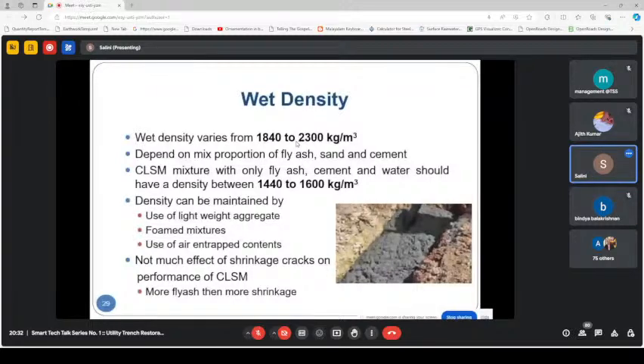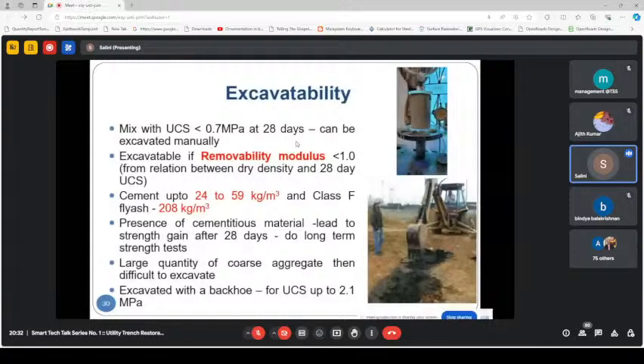Then excavatability, as I said, is very important. Sometimes what will happen is we add more cement, we add more fine aggregates, and the compressive strength becomes more than what is required. In such cases, it becomes very difficult to excavate. And then if there is some leakage, or if some widening is happening and we need to relocate the utility, it becomes very difficult. So make sure that strength does not go beyond what is required. In order to show that we have done it properly, we may increase the strength, but that also will lead to harm. So the strength should be maintained.